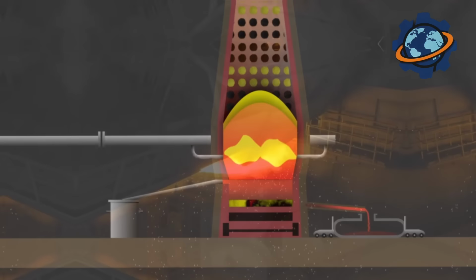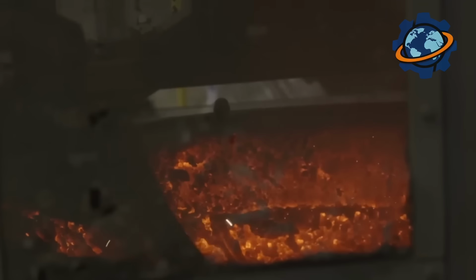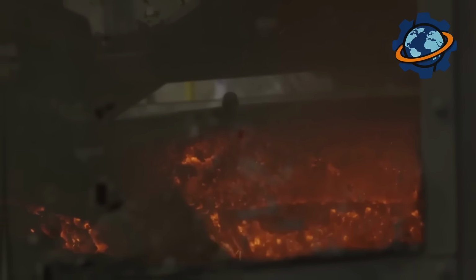Next comes the basic oxygen furnace, where pure oxygen blasted at supersonic speeds through 3-foot diameter lances burns away excess carbon in 17 minutes. Flames shooting 70 feet high. Temperatures hitting 3,200 degrees create hurricane-force winds inside steel vessels holding 350 tons of liquid metal.